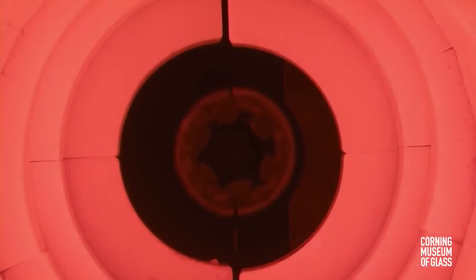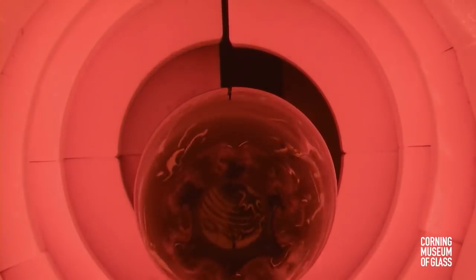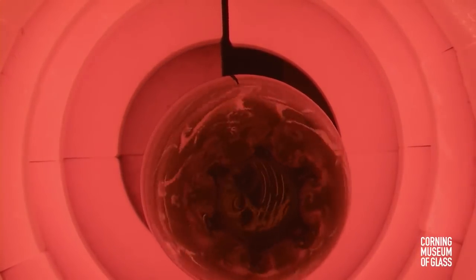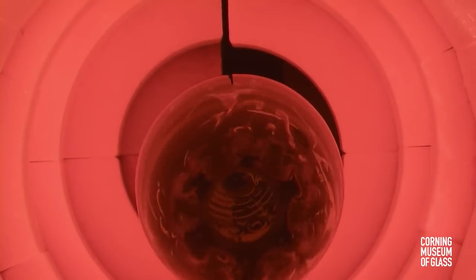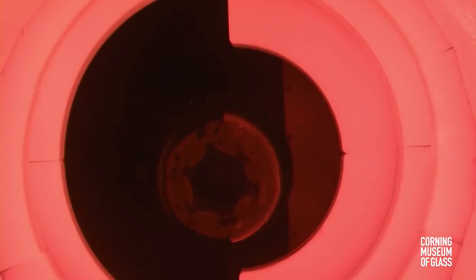On Mika's piece, the inside and the outside are going to be vastly different in temperature. So we put it in that oven, we hold it at 900 degrees for many, many hours so that everything gets to that temperature. And then we slowly cool it. And the thicker it is, the slower we cool it so that everything changes temperature at the same rate. So that the outside doesn't cool quicker than the inside, because it's that differential that's going to cause the piece to break. When one part's 500 degrees more or less than another part, it causes so much strain in the glass that it'll break. So the annealing takes the stress out of the glass.